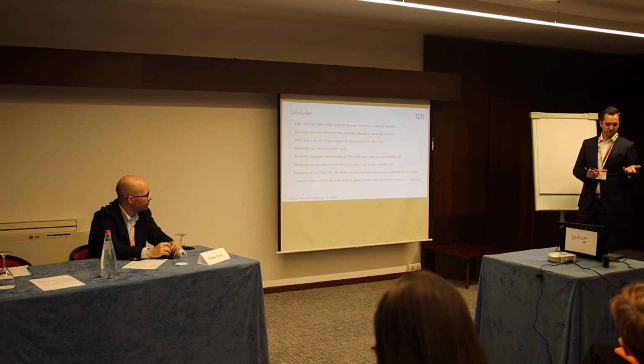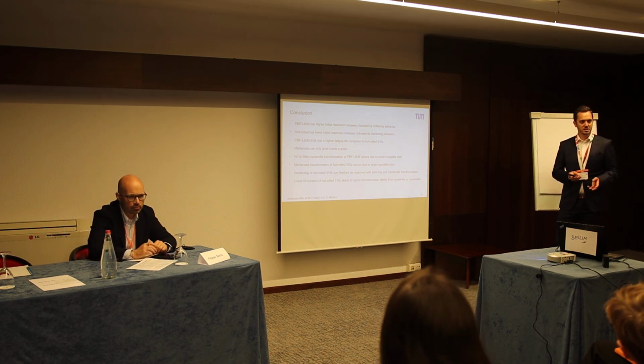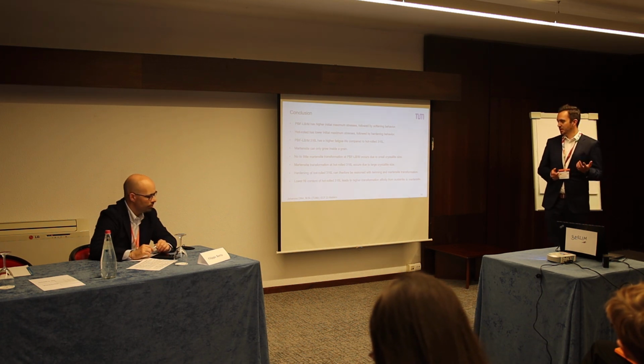One thing I have to mention in the end, for the EBSD measurements and also for SEM measurements, we can only see a small picture of it. So we cannot really say that it stands for the overall material. So that's why we conducted a few weeks ago some measurements at the electron synchrotron in Hamburg to do in situ fatigue testing. And there we could measure the dislocation density and also the phase transformation to take a look at the overall structure, because we were able to take a look at the whole measuring area during testing. It was quite nice to see. So keep that in mind.